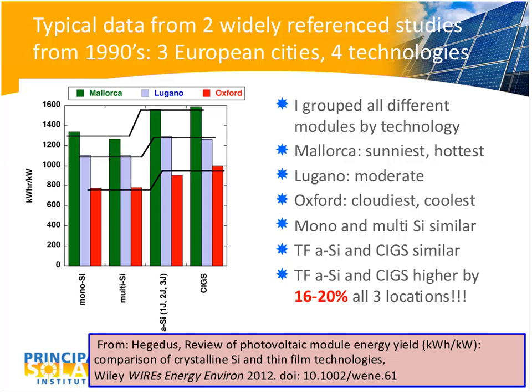Then if you go from technology, you see that the 2 crystalline silicon or mono and multi-silicon technologies are pretty similar in both locations. But then when you go to the 2 thin films, things jump up. And in fact, both the amorphous silicon and the CIGS have, on average, 16 to 20% higher kilowatt-hour performance in all 3 locations. And like I said, these values have been widely referenced and quoted. They were done by reputable groups, but the magnitude is just a little bit too big to be believable.